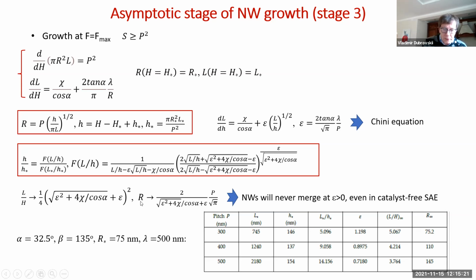And for R, the radius, it is proportional to just the distance between the nanowires. So this would relate to coalescence or merger of nanowires. What I can see from this solution is that nanowires will never merge, provided that there is a diffusion from the sidewalls to the top, any diffusion. Even in the selective area grown nanowires, catalyst-free, where the second term is actually 1. So this is very important. Nanowires will never merge if there is a diffusion.